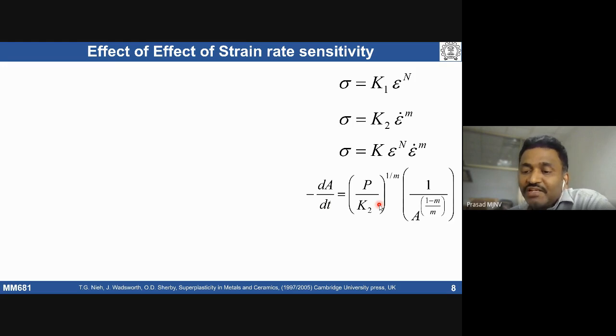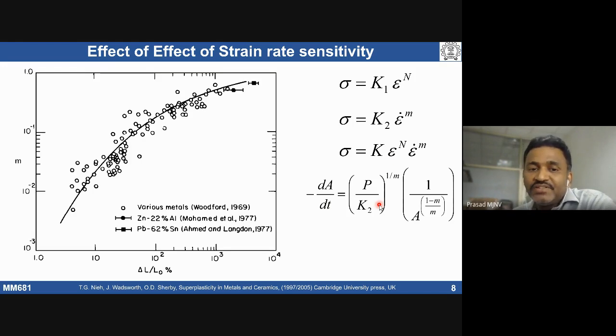That's why people have observed, by taking various materials and putting them together, how the m value and tensile ductility, elongation to failure, delta L by L naught, vary. Look here: the higher the m value, the higher the tensile elongation. Both are on log scale, x and y. So this kind of relationship was found between strain rate sensitivity and tensile ductility.